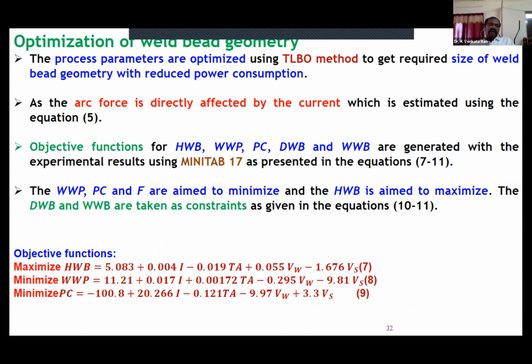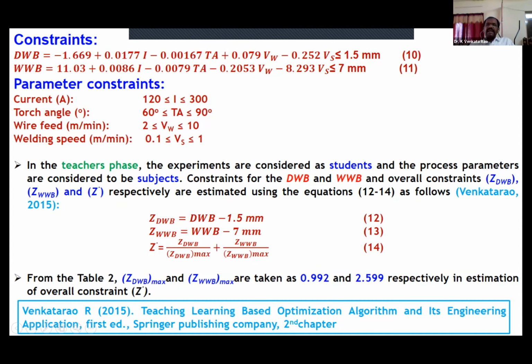Here, the height of weld bead is maximized while minimizing the width of weld pool and power consumption. Keeping these as constraints, the depth of weld bead should be less than 1.5 mm, and the width of weld bead should be less than 7 mm. Based on the capacity of the robot and previous research works, these parameters are bounded. So the current should be within these two limits only: it should be 120 and should not be more than 300. I already explained this based on the previous experimental work.